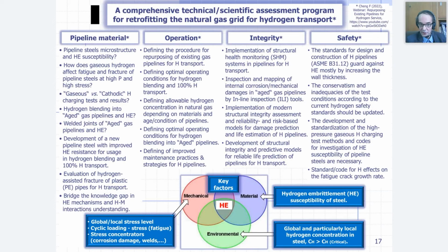So the most important mechanical factor is a global and local stress level, pressure cycling in pipelines, cycling loading, which generally produces fatigue, and as I previously explained, enhanced fatigue due to hydrogen embrittlement. We also need to investigate the presence of stress concentrators like existing corrosion damages in aged pipelines and welds. What about material? Hydrogen embrittlement susceptibility of steel is very important, and it's different for different types of steels depending on the microstructure and numerous other parameters. And an environmental factor is to investigate and determine the global and particularly local hydrogen concentration in steel, and to compare that concentration with so-called critical hydrogen concentration in order to avoid the sharp drop of mechanical property upon activation of HELP and HEDE mechanisms. So what about what we need to do related to pipeline material, operation, integrity assessment and safety?